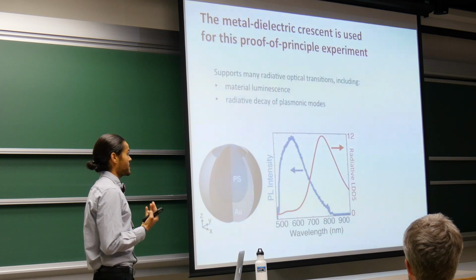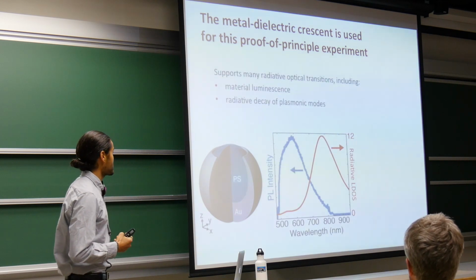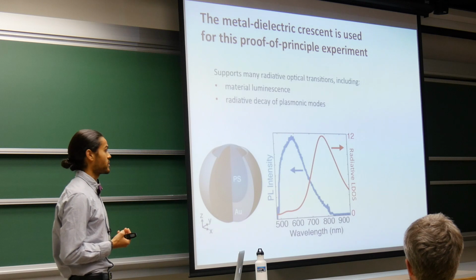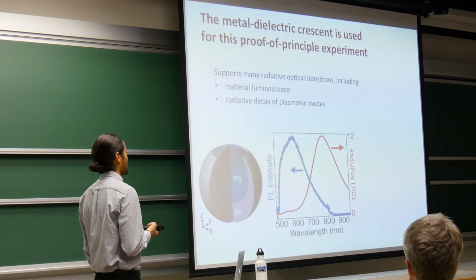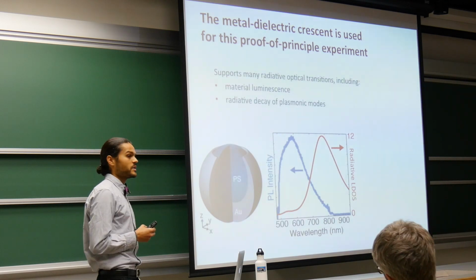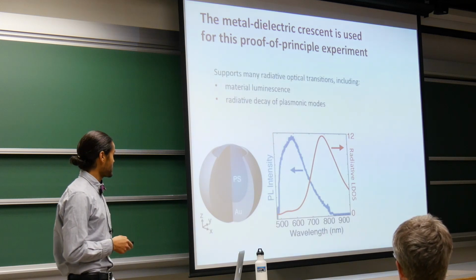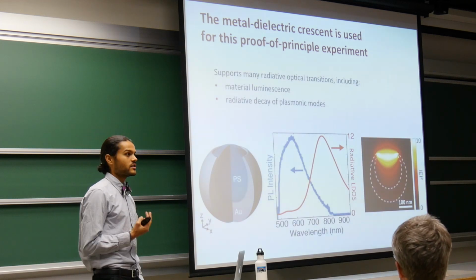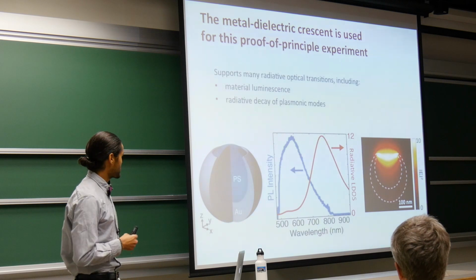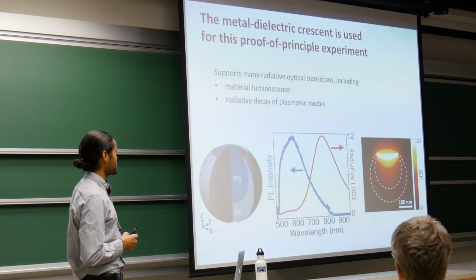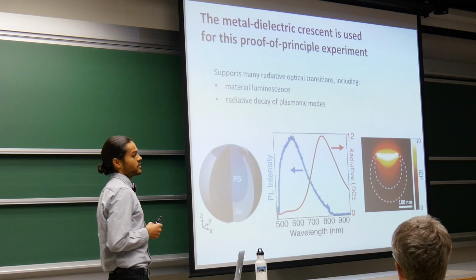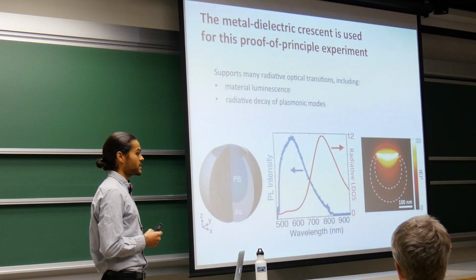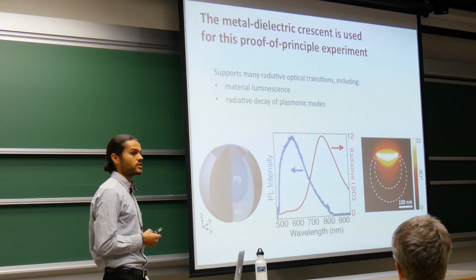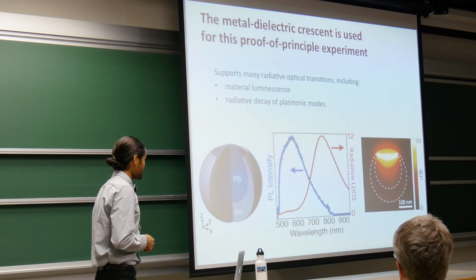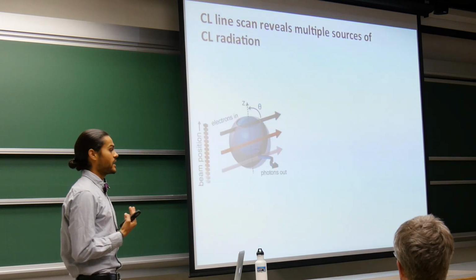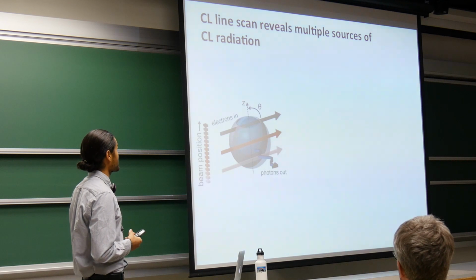The other process that I've described in the previous two sections is this plasmonic mode supported by the crescent. In this particular geometry and with these materials, this mode peaks at a wavelength of around 800 nanometers, and we can see, based on the near-field plot, which looks pretty familiar from the prior two topics, that this mode is characterized by a strong dipolar resonance at the tips of the structure, which leads to a pretty strong field enhancement. So let's look at how we can probe these different properties with cathodoluminescence.